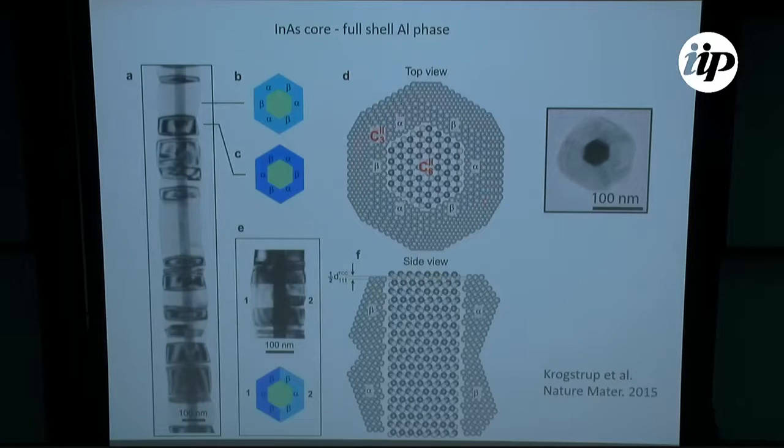This is relaxed structures, just giving the bulk lattice constants, and they really match up in all dimensions to one hybrid coherent crystal with a 3:2 ratio. That's just from a material science point of view, that's nice, but I don't know if it's important for what we're doing. You can also see here there's a cross section of the wire. It follows the facet of the wire in here, so it goes into the same overall crystal symmetries.